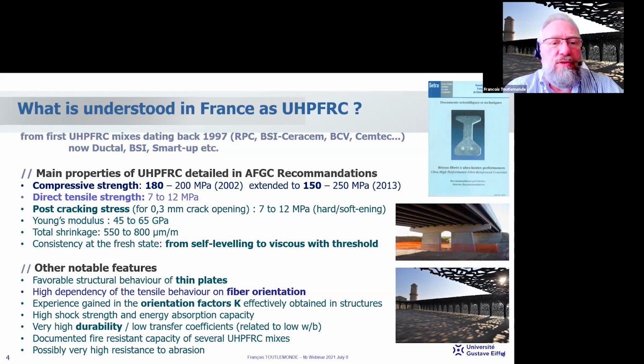The direct tensile strength of this material is from 7 to 12 megapascal, and what's most important, the post-cracking stress for a typical 0.3 millimeter crack opening is from 7 to 12 megapascal. So there is either hardening or softening behavior, but one of the key features of this material is that we can account on tensile capacity.